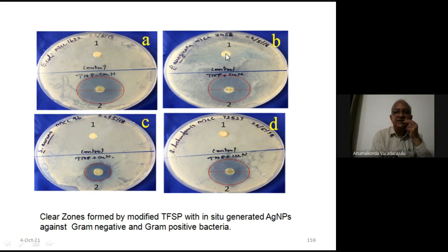One is designated for unmodified powder, and 2 is designated for the nanocomposite powder or modified powder with in situ generated silver nanoparticles. Here they showed very good antibacterial activity by formation of these clear zones.